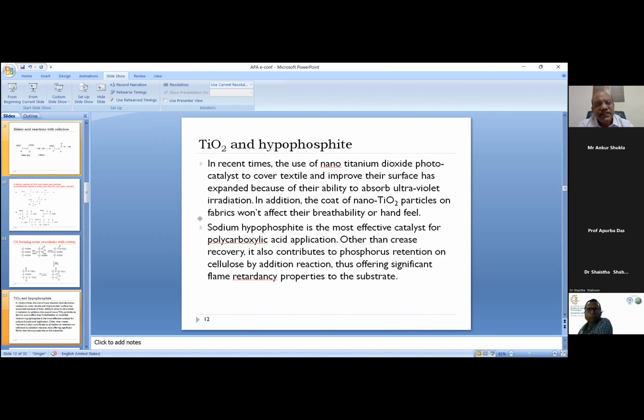Okay, then besides this, the other chemical which is used in this particular experiment is titanium dioxide. In fact, the use of titanium dioxide has broadened in the last couple of years. Earlier it was mainly used as a photocatalyst, but now it is found that it has good applications even in UV protection. And sodium hypophosphite is a catalyst which is particularly useful for polycarboxylic acid application. And other than that, because of the phosphorus retention, it can also have significant fire retardancy.